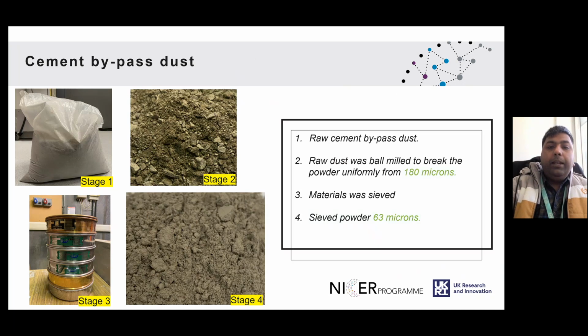So we basically begin by collecting the raw material, that is the cement bypass dust here, which is shown here. Now, for thermal spray to be effective, what we need to first of all do is to characterize and also to make sure that the powder is properly homogenized and filtered and sieved so that it will have homogeneity while it is going through the hose and the nozzle subsequently of the thermal spray gun.